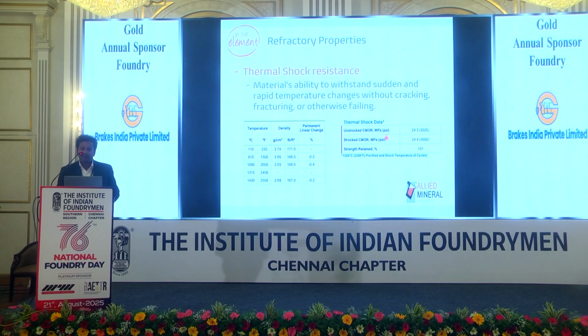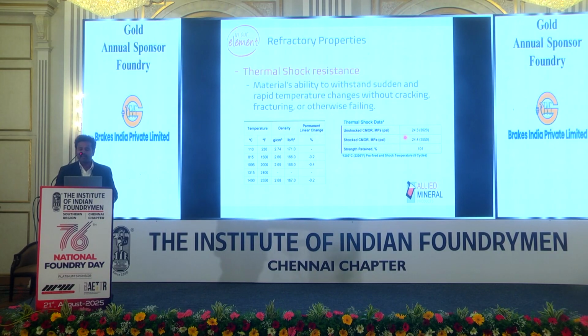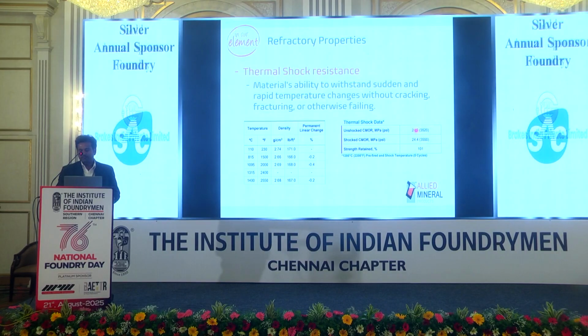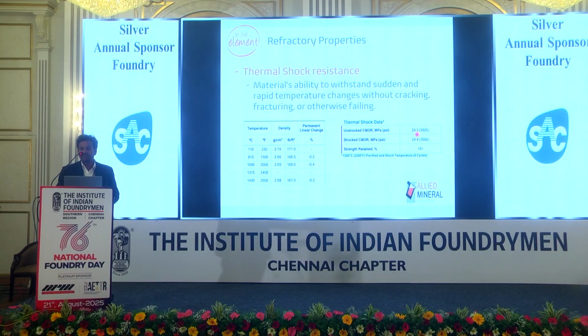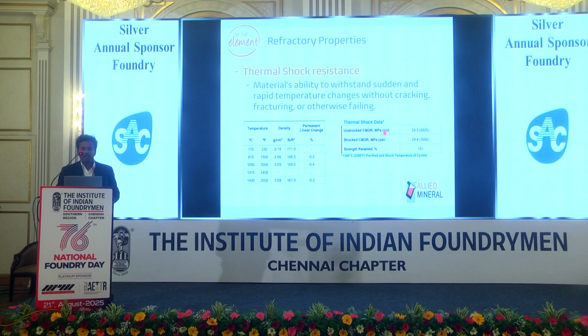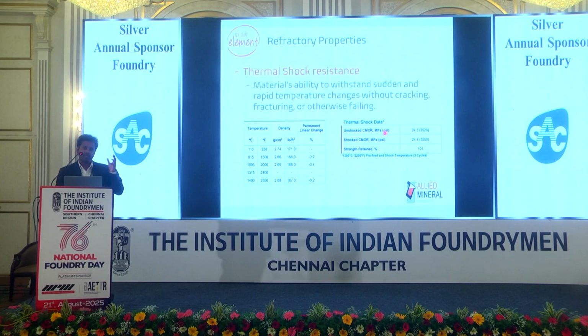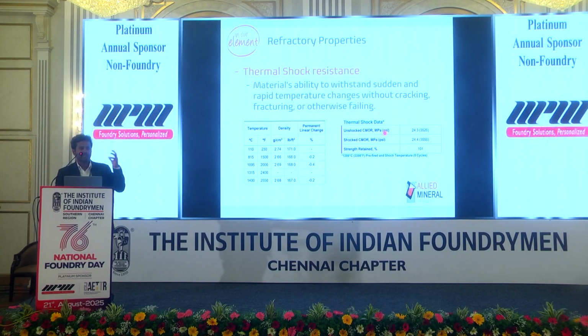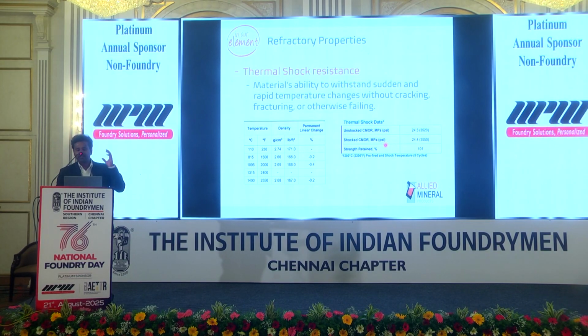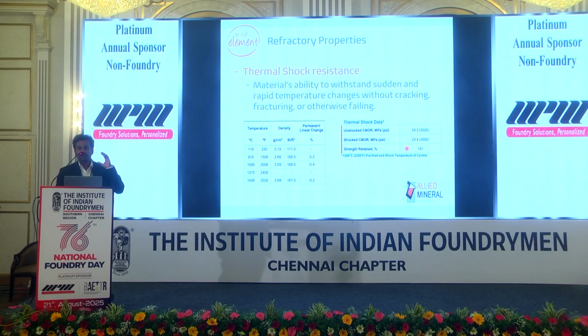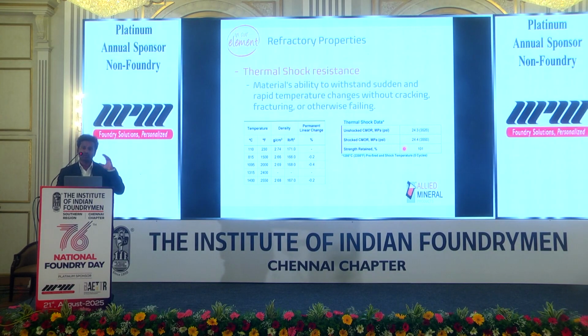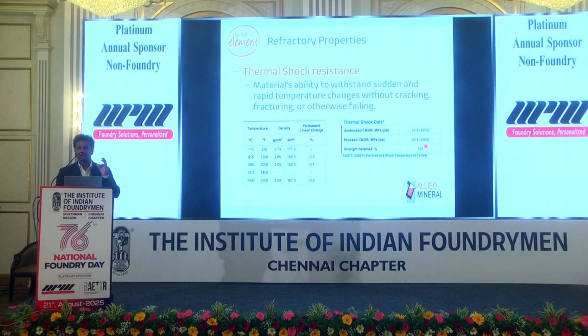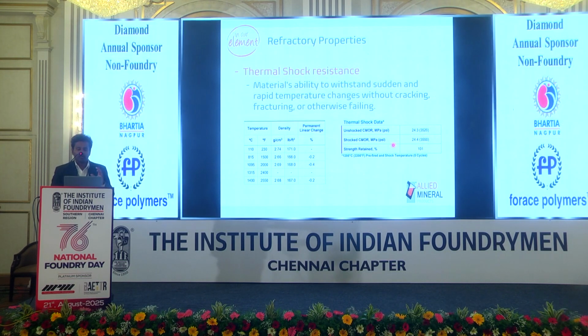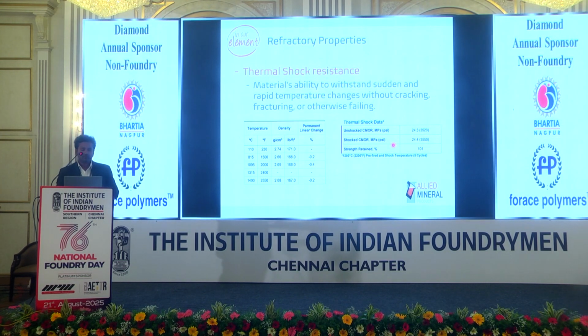This sample was analyzed unshocked, and it has a CMOR of 24.3 megapascal. This particular specimen was cycled 5 times around 1200 degrees Celsius, and again the test was conducted and the MOR was seen. The difference is not much, which means this product will withstand the thermal shock. The strength retained is almost 100%. So this product is thermally stable.